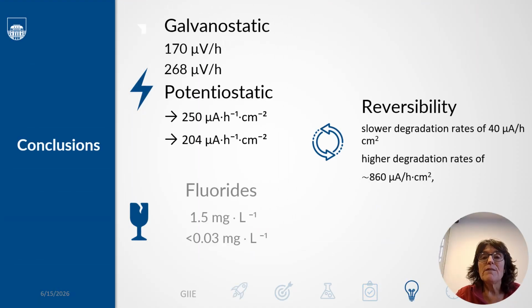We now summarize the main conclusions. First, under potentiostatic operation, the Nafion 1110 with platinum black assembly degrades at about 250 microamps per hour per square centimeter, while the Nafion 115 with iridium-ruthenium oxide assembly degrades at about 204 microamps per hour per square centimeter. Under galvanostatic operation, we observe voltage drift rates of about 170 to 268 microvolts per hour.